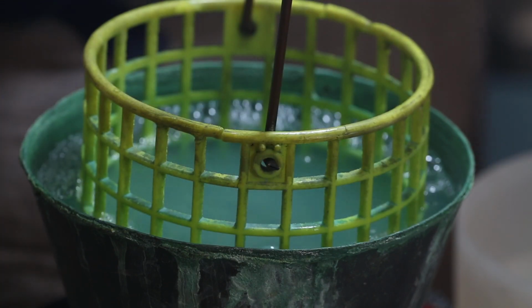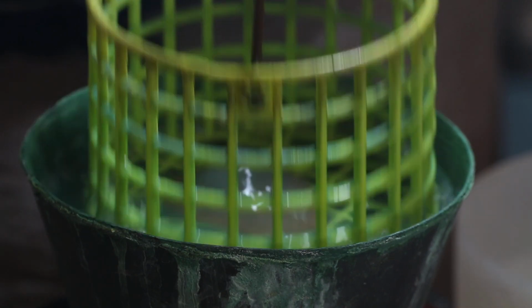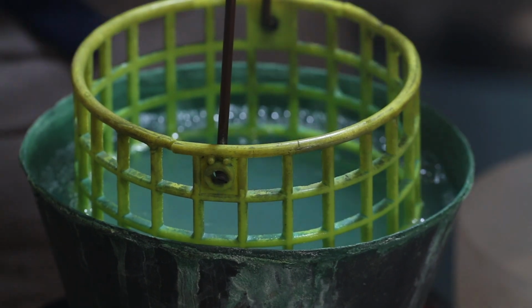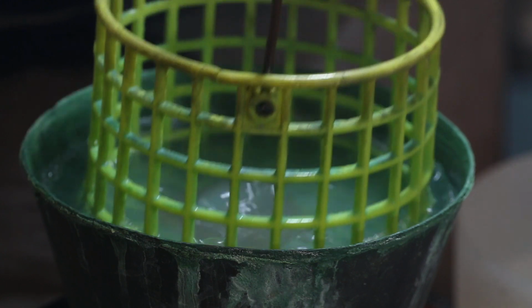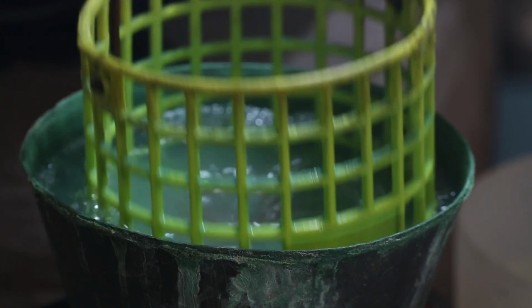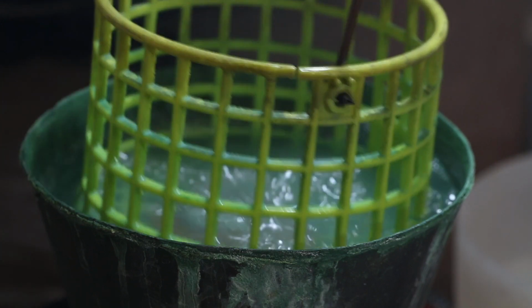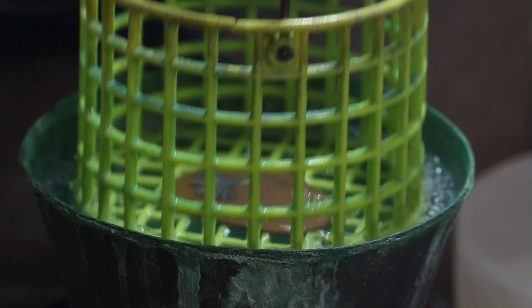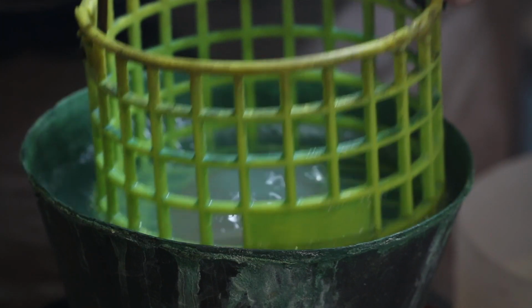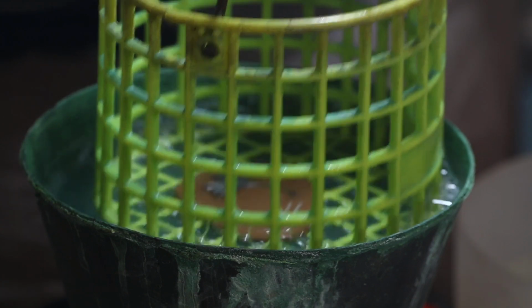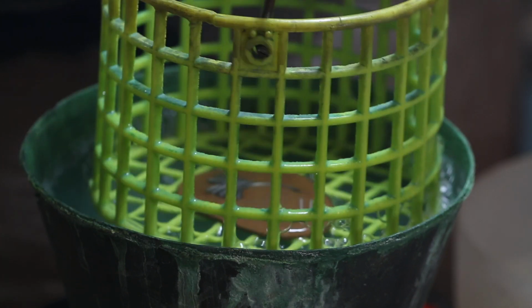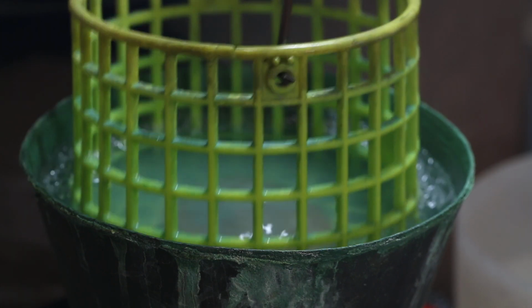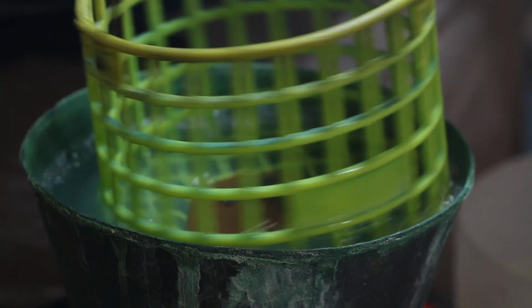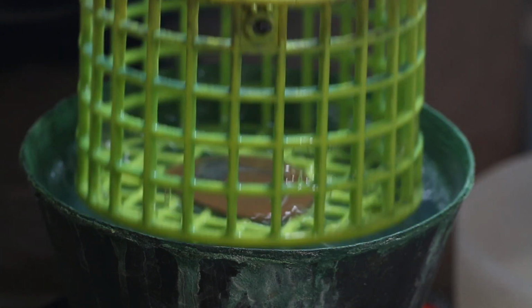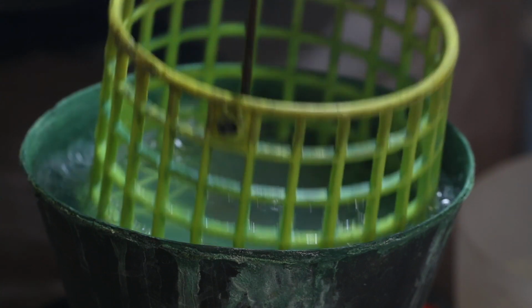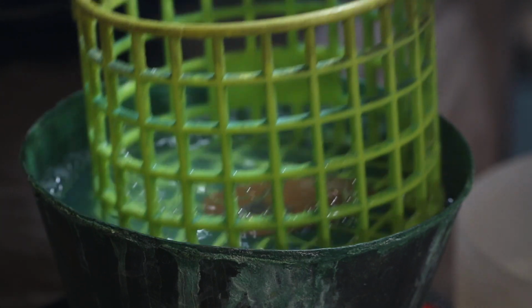As I say, the actual colour and the depth of colour, just speaking about the copper in this instance, but it's true to a certain extent of the Shibuichi and Shinshu brass type alloys. If we speak just of the copper, the actual colour and depth of the patina is dependent on the thickness of the cuprite layer and the size of the individual particles. And those are factors that are affected by the surface finish to a certain extent, the hardness of the metal, I believe, the extent to which it's been forged and worked, and perhaps even the purity of the metal.